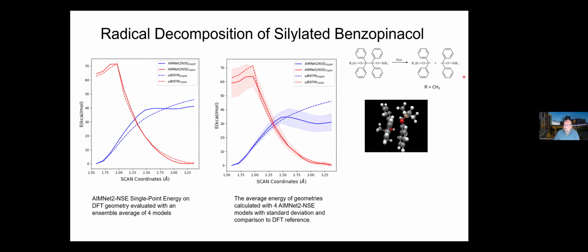Where this initiation of the radical reactions goes from what's called the singlet state to the triplet state. What you see here is a comparison of this reaction profiling with DFT versus AIMNet. Essentially, you start from a singlet state in blue, but as this reaction goes, you see formation of two radicals, and therefore you end up in a triplet state. This is where it crosses, and essentially the reaction switches the potential energy surface and goes into the triplet state. And therefore, for the first time, you can allow the simulation to be done with the neural network.